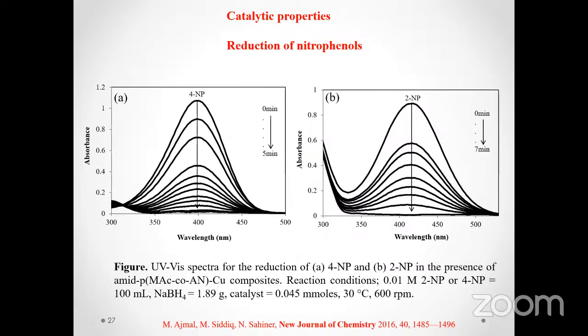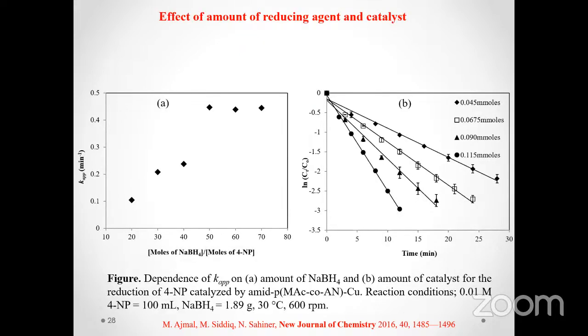And we also observed strong catalytic activity, as can be seen here. 4-nitrophenol and 2-nitrophenol can be reduced in the presence of these catalysts. And there are different parameters which can be used to control the rate of the reaction. For example, we can change the amount of the catalyst, and by increasing the amount of catalyst, the rate of reaction is increased, which can be seen from this figure, that as the slope of these lines through the first order graph increased, the rate of the catalytic reaction is also increased.